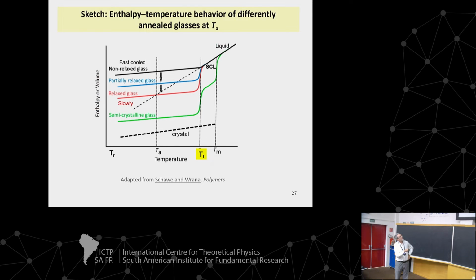However, let's say that we came to this path here. We fast cooled, and we were able to avoid crystallization. The melting point is here. This is called the fictive temperature here. We form the glass. If we stop here at some temperature of study, this glass will relax and relax, and reach this supercooled liquid area again. And if we continue to heat it, eventually it will crystallize. So this glass here is relaxing. Even at room temperature, it's relaxing. All glasses are relaxing. The structure is accommodating. Of course, at very low temperatures, it will take zillions of years. It will take a very long time.